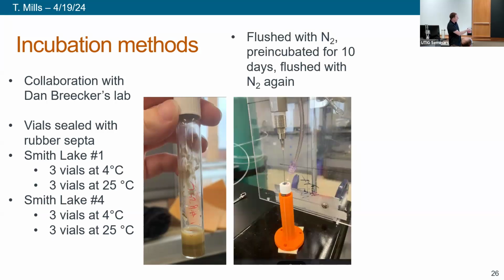And so what we do is we'll load our sample into our vial, and then we'll poke a needle down through there and we'll flush the headspace with nitrogen. And once we flush the headspace with nitrogen, we have an atmosphere in our vial that's totally anaerobic, where there's no oxygen or CO2 present, or methane. And then we're able to start our incubations. And so we did incubations for 15 days, 35 days, and 59 days. And then we collected the headspace gases on those increments of time.